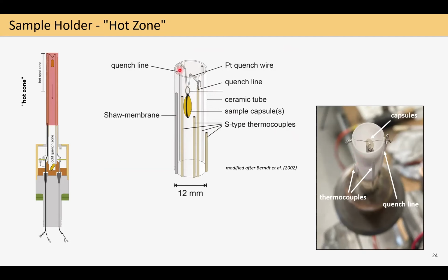And one of these two quench lines is then via the cold zone and the closure head connected to the outside of our vessel. And when we apply there an electric power source and a short pulse, we will create a short circuit in our system, thereby fusing this thin platinum wire up here, allowing the capsule to fall down to the cold zone, resulting in cooling rates exceeding 100 degrees Celsius per second.